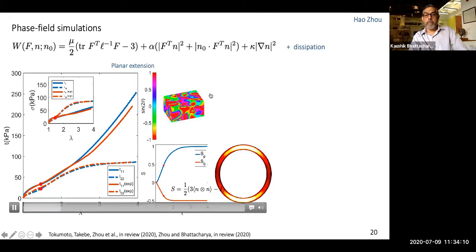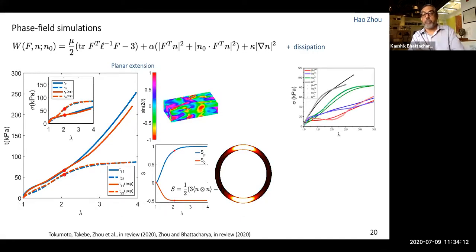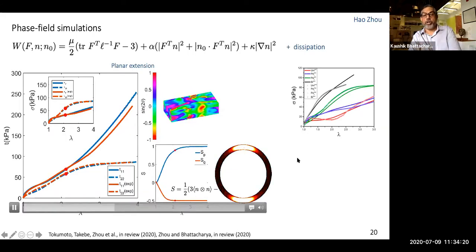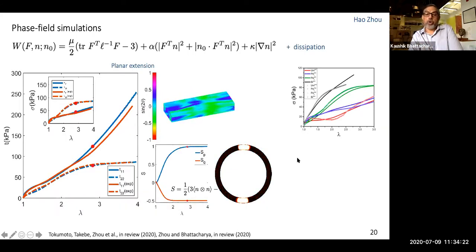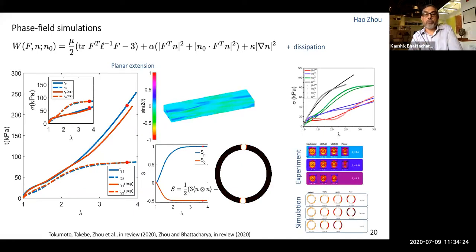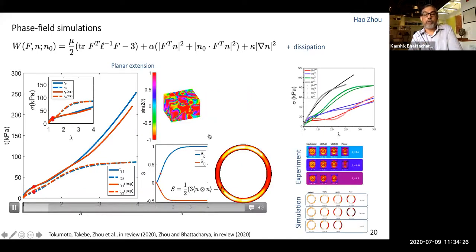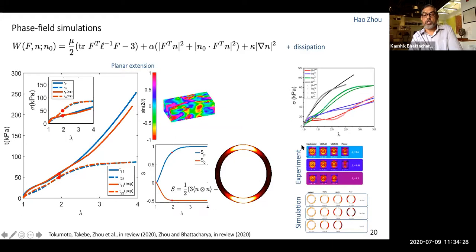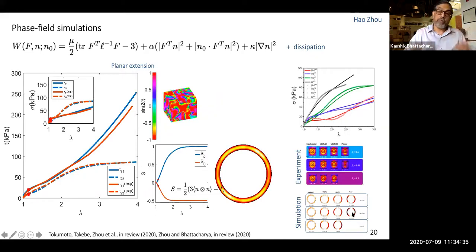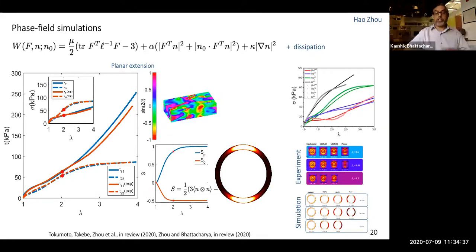And so here's some more comparison. With just 5 parameters, you're able to describe a whole range of experiments which were done with this material. And you can also, by using X-ray scattering, probe the distribution of the directors, and you see that this is the experiments and this is the simulations. And again, you get a very good agreement between these two.